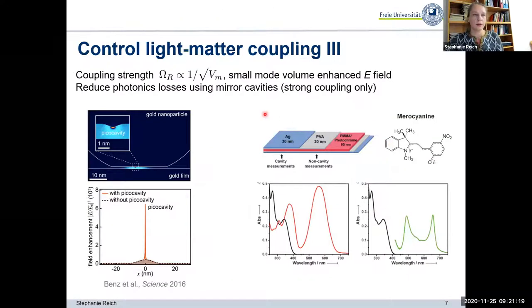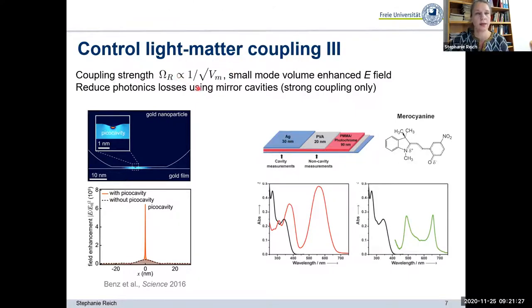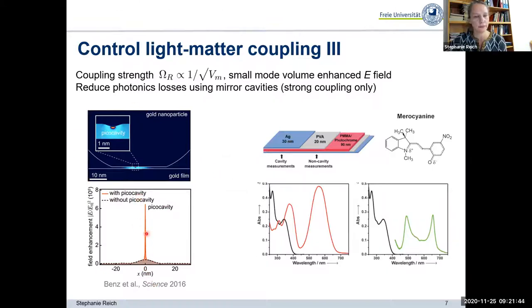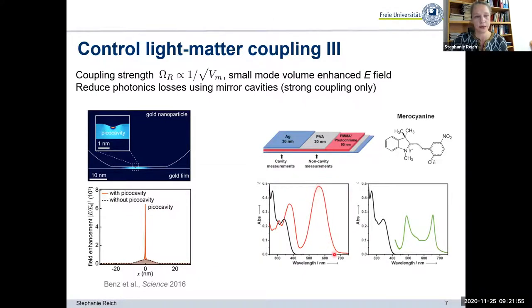The third knob is the volume of the photons. There are two ways people do this: you can take plasmonic particles that focus electromagnetic fields into nanoscale volumes, giving a huge enhancement that drives light-matter coupling; or you can build a cavity. This is shown for the case of merocyanine absorption — measured in a film without a cavity, the spectrum is just a single absorption. When you move to a cavity, you see the splitting into upper and lower polaritons.